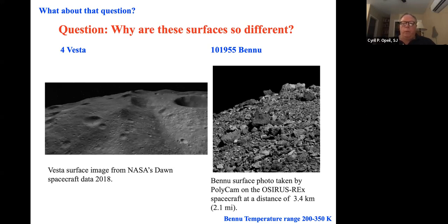If, in fact, Bennu has phyllosilicates, CM2 or CM1, CI carbonaceous chondrites, there is the possibility that we've actually looked at the mechanism. Just like pouring hot boiling water in a cheap coffee cup, you can crack material. You can crack a cup by not being able to heat or cool a particular material evenly. That's why a cheap china cup can crack, because you heat one part. One way you stop that is you put a spoon in so that the heat is taken by the spoon as opposed to the ceramic.